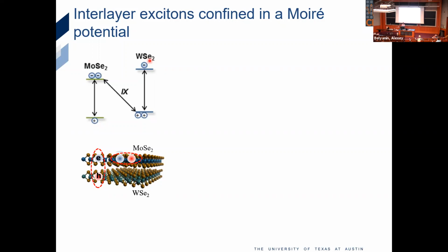So when I put them together, you always have to ask how the bands, the conduction band in one material and the valence band in the other material, line up. Turns out in these materials, typically they have what's called a type 2 band alignment, meaning the minimum of the conduction band sits in one layer, the maximum of the valence band sits in the other layer. My undergraduate students said, you just understand the holes as if they were the bubbles in your drink, in your Coca-Cola, and then the holes just flow to the top, electrons sink to the bottom of this layer.